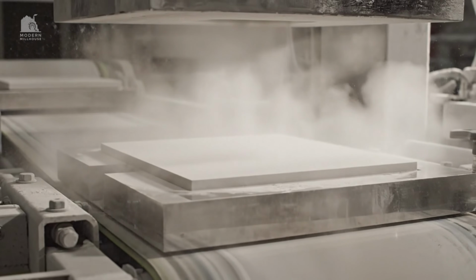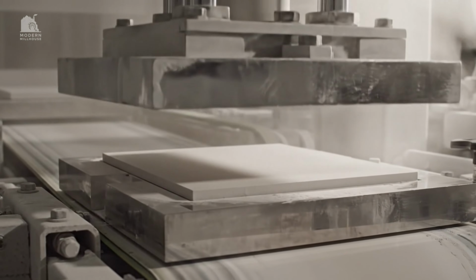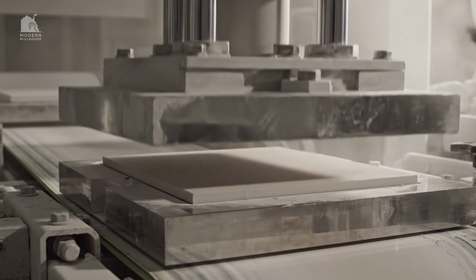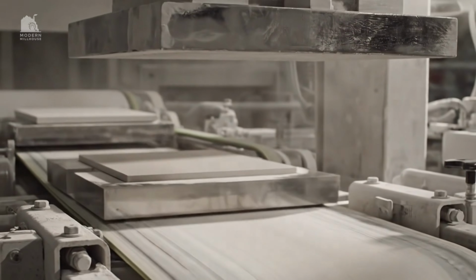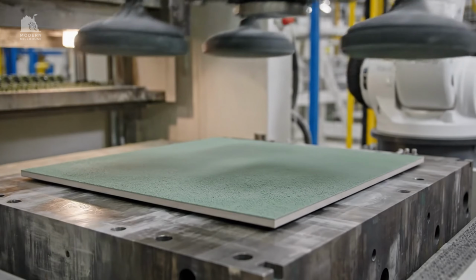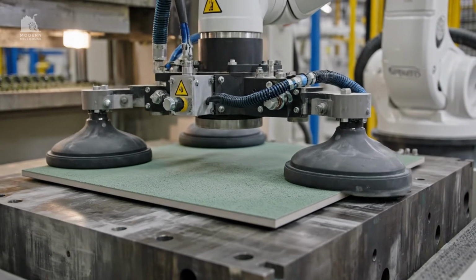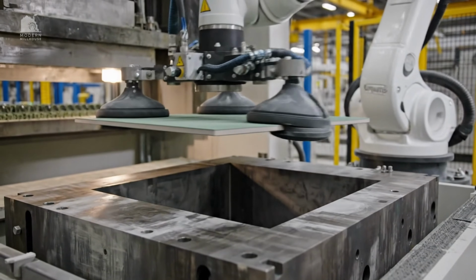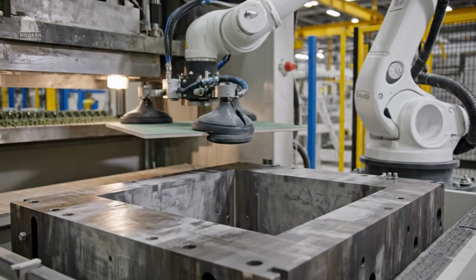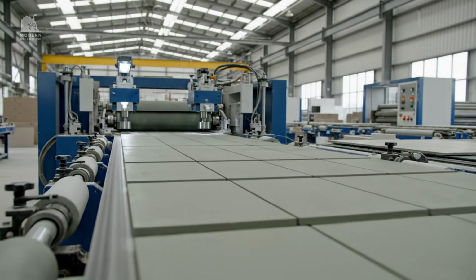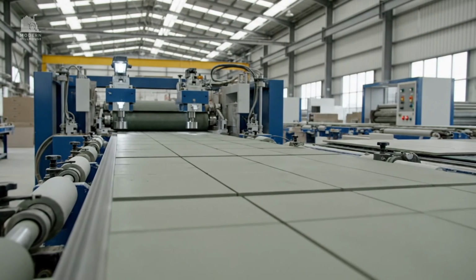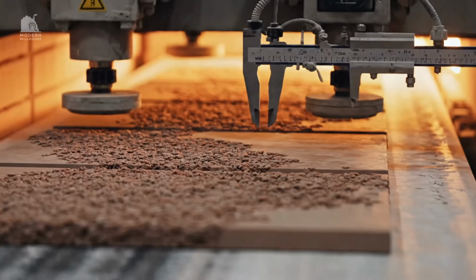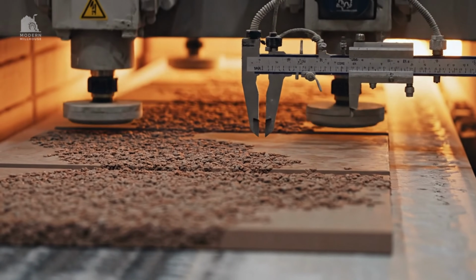If the top surface is denser than the bottom, tiles can curl during firing like a bimetal strip. To prevent this, presses tune filling, vibration, and pressure ramps so the compact is uniform. Tiles may pass under edge rollers or light calibrators that remove burrs and improve stacking. Plants continuously measure thickness and weight to catch drift before it becomes a kiln-wide problem.